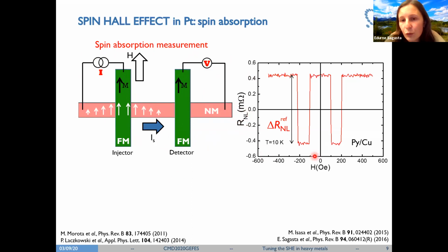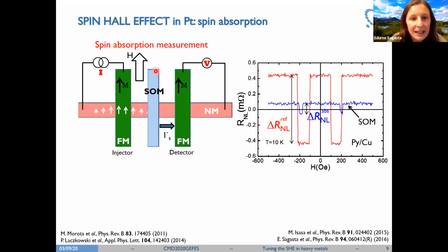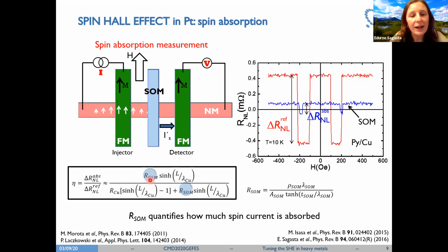Now if we sweep the magnetic field, we are able to attain the parallel and anti-parallel resistance values of the two ferromagnetic electrodes. And from the difference, we get the spin signal. Now, if we fabricate another lateral spin valve in the same conditions, but adding a spin orbit metal in the middle, and we perform exactly the same measurement, what we see is that the spin signal that we obtain is much smaller. So basically what we are seeing here is that the spin orbit metal is absorbing part of the pure spin current that is flowing in the non-magnetic metal. This is why we call it spin absorption. So from the ratio of the two signals, we are able to quantify how much spin current has been absorbed in the spin orbit metal.